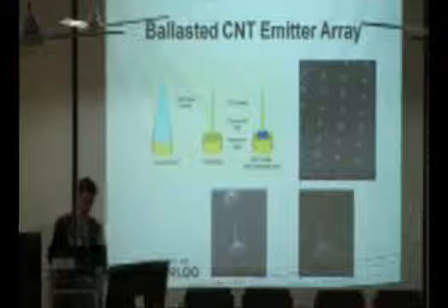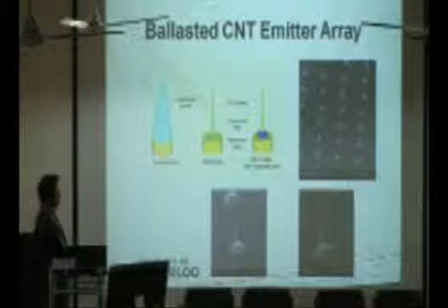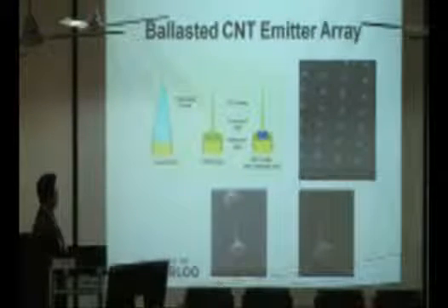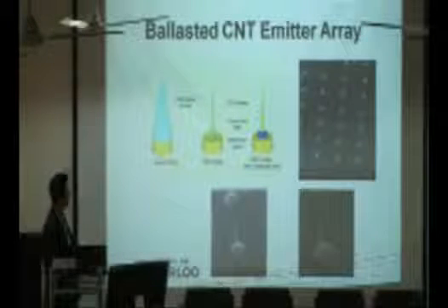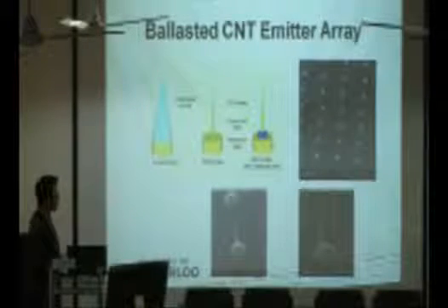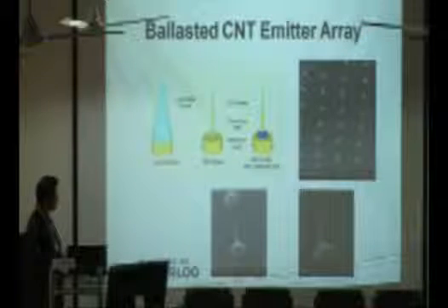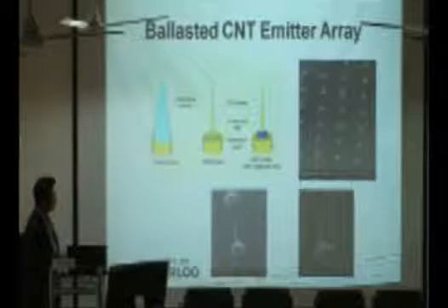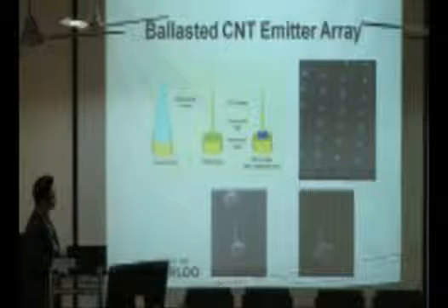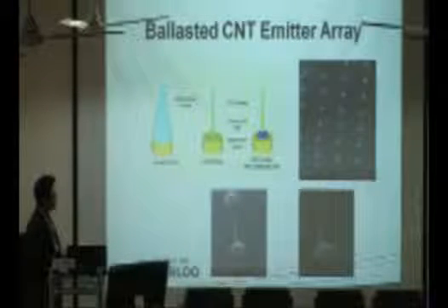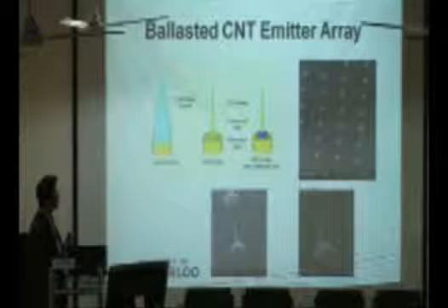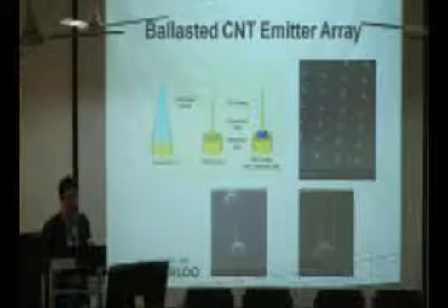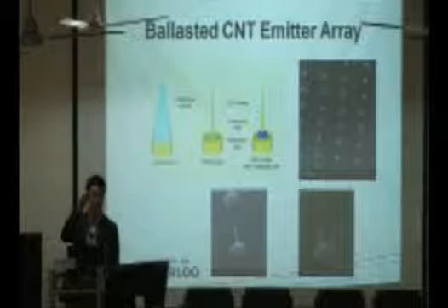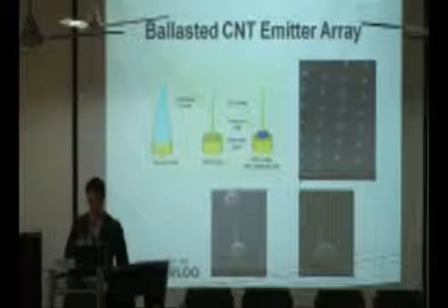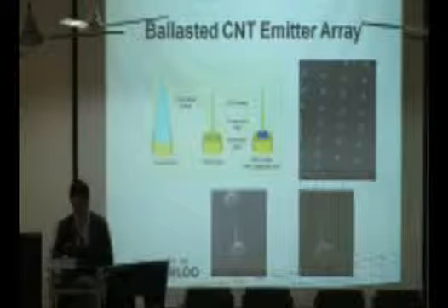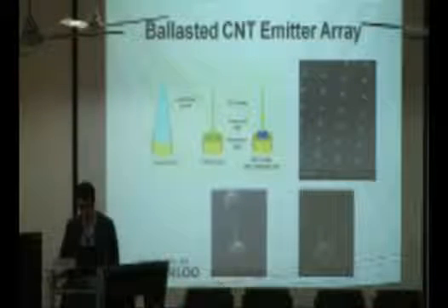Now, through many experiments, it's actually more trial and error, we have done this so many times that we have come across this new architecture where on the bottom electrode, we deposit a contact pad that has really good adhesion to CNT. So at this point, we can guarantee the uniformity of the current, but at the same time, we guarantee the mechanical integrity of the CNT strand.